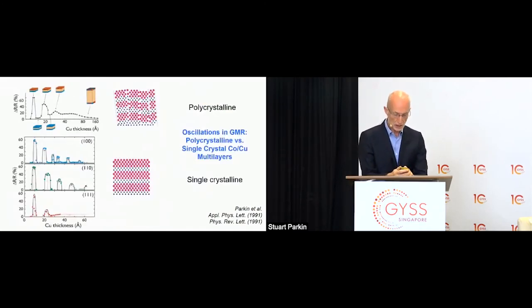And one of the reasons I could do this was I demonstrated that in a superlattice or a multilayer, as you change the thickness of the copper layer, as shown here on the left-hand side, you can see this plots the magnitude of this giant magnetoresistive phenomenon. In other words, what is the percentage change in resistance of the superlattice when the moments in the superlattice have their neighboring moments antiparallel versus parallel?